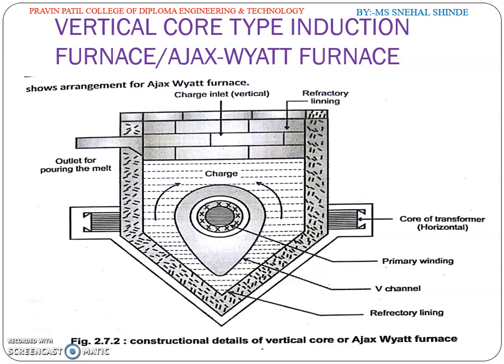The circulation of the molten metal takes place in V channel due to convection. The high temperature metal goes up and low temperature metal comes down. Thus, the stirring action is automatically obtained. This causes the homogeneous heating. It is used up to 2 tons, commercially used for melting non-ferrous metals like copper, brass.